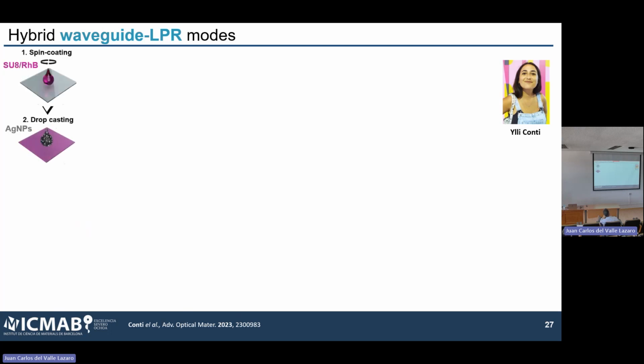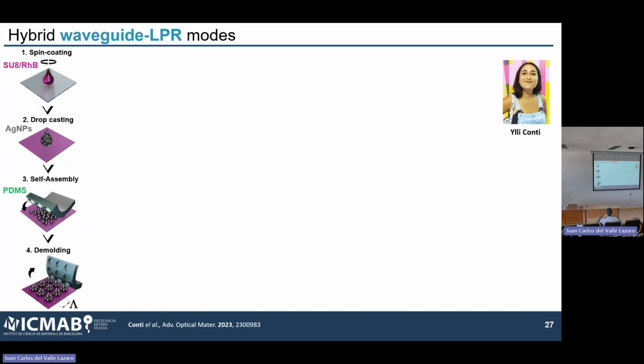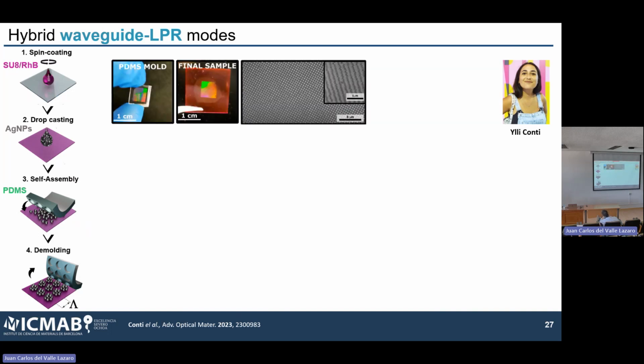And so what we did was create a thin film, in this case containing rhodamine B, because we wanted to look at how we can use this plasmonic metasurface to modify the fluorescence of the rhodamine B system. We created a thin film of around 250 nanometers of SU8, which is basically a photoresist containing the rhodamine B.